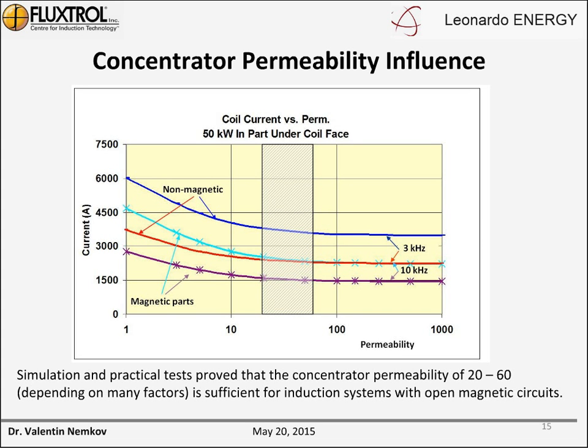When we have no concentrator, permeability is 1, and we have a much higher current demand. The top curve shows that it's more than 2 times higher, 2.5 times. This current demand drops when permeability grows. But this effect saturates relatively quickly, and at permeability equal to 20-30, we have almost all the effect already achieved, and a further increase of permeability does not give any advantage in terms of current demand.